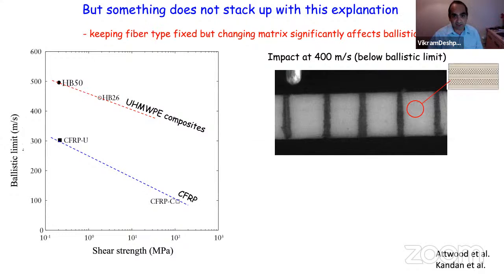So we keep the fiber strength fixed and vary the matrix, i.e. change the shear strength of the matrix, and this is the ballistic limit. And so this is the ultra-high molecular weight polyethylene composites. As you increase the shear strength, the ballistic limit decreases. And the same thing with carbon fiber composites, that as you increase the shear strength, the ballistic limit decreases. So something is telling you that there's something incomplete with that explanation.